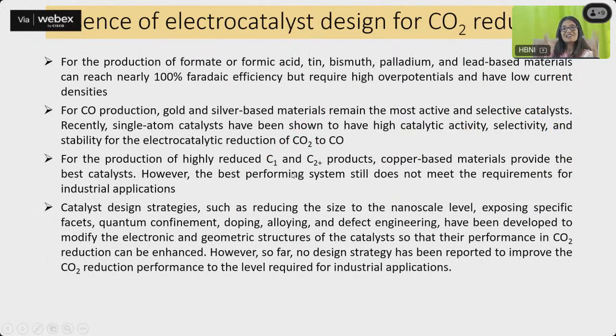So in essence, what is the electrocatalyst design for CO2 reduction as of now, what we have seen? For the production of formate or formic acid, tin, bismuth, palladium and lead-based materials can reach nearly 100% Faradaic efficiency, but they require higher overpotentials and have low current density. For carbon monoxide production, gold and silver-based materials remain the most active and selective catalysts. Then for the production of highly reduced C1 and C2 plus products, copper-based materials provide the best catalyst, as I showed in the first slide on the carbon dioxide reduction reactions.